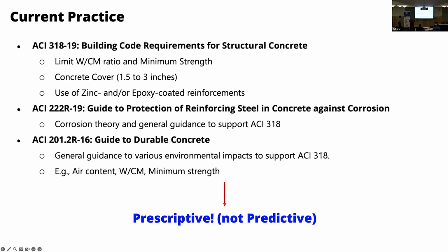So this is quite the summary of the current practice. So to care about the corrosion, what we have been doing. So ACI 318 building code just specify about the concrete material. How? Just setting the limit of the water cement ratio and the minimum strength. So in other words, making concrete stronger to slow down the corrosion process. Another way to do that is putting a little bit thicker cover depth. That also slows down the penetration of the chloride. As a result, it can slow down the corrosion process as well.